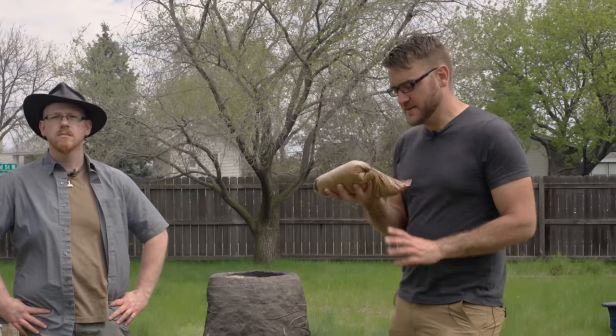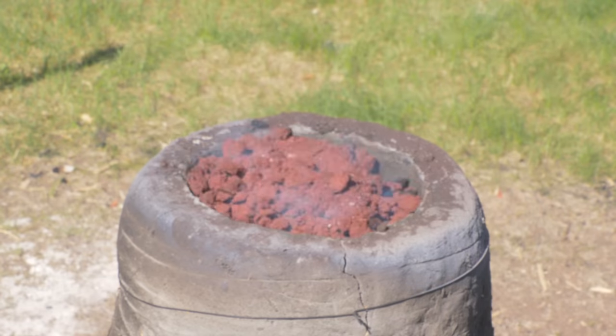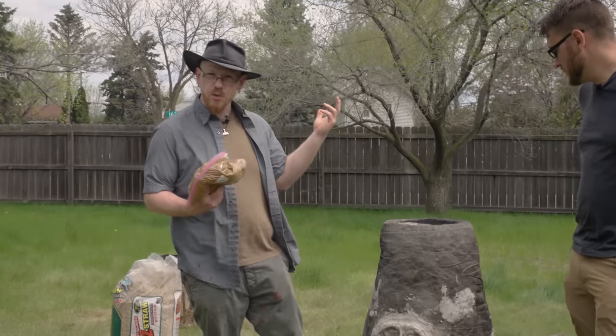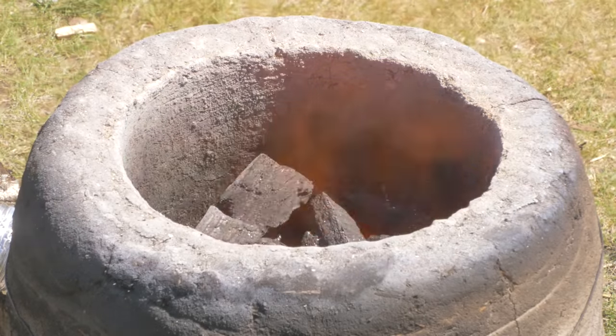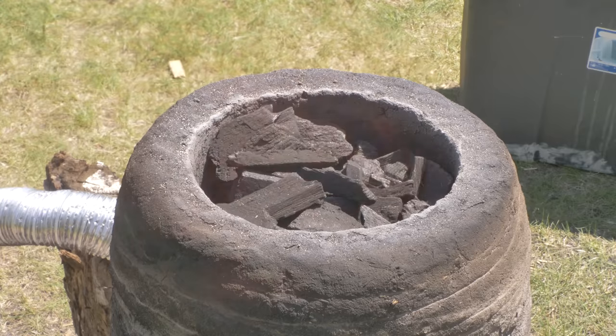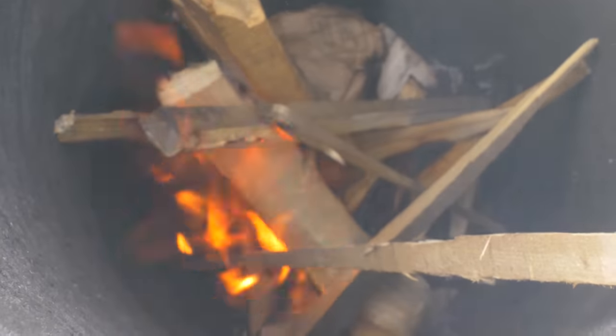Back from Utah, after a really grueling hike in the mountains, I was able to get a decent supply of bog ore — the kind a lot of Vikings used for smelting iron. I'm here with Joe who has been working on recreating a Viking-style bloomery. We'll roast the ore up and use it as some of our charges today. We'll burn off the water and should see a bit of a color change as the oxides present themselves as much more red after it's roasted. I built a Viking-age short-stack bloomery furnace. It should take about six hours total and hopefully at the end we'll pull a nice lump of iron. We're creating a layer of charcoal fines or charcoal powder below the tuyere — this will give a nice pre-filled area for the bloom to start consolidating on and forming that liquid bed of slag. Once it's got a nice solid heat going we'll start adding two-kilogram charges of ore and charcoal at a time.